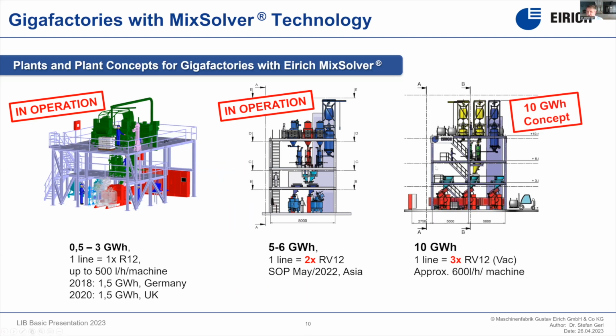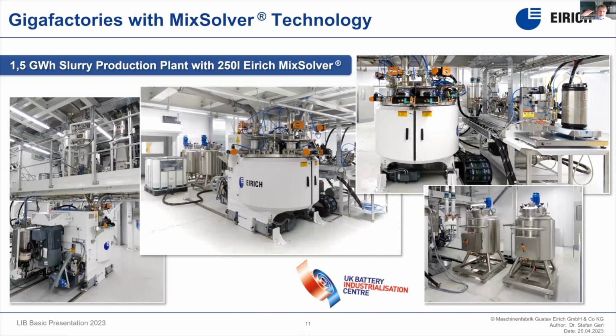This is then the option with 3, and we can go up to 4 machines in a row. This means you're using the dosing system in the best way, and then distributing between the 3 or 4 machines, which are then working more or less in parallel. By this, we can reduce the footprint dramatically. And even if the height is a little bit higher than with a pneumatic system, we are still much lower in height compared to these extremely big planetary mixers.